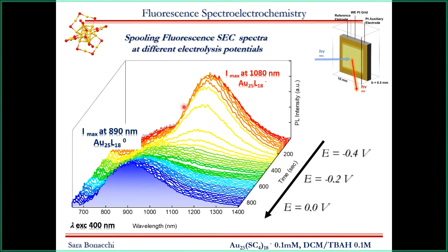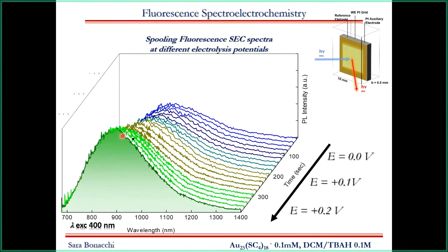And if we go further and apply an even more positive potential, we observe instead an increase of the emission without any shift in the emission. So again, there is the possibility to clearly identify the neutral form and the plus form as a function of their quantum efficiency, basically, just playing with the electrochemical potential inside our spectroelectrochemical setup.